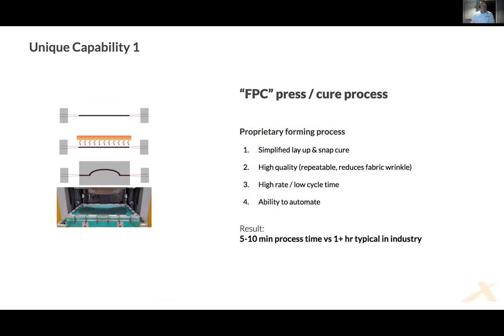The first area that we tackled is called the FPC process. This process is no longer using an autoclave and a slower ramping up, dwell and ramp down process, but is now a fast press curing under vacuum. This allows us to reduce the time taken to manufacture the component and subsequently the impressions per tool, so increasing volume. We typically see the whole process down to about 9 minutes at the moment, and there's still further that we can do. That's on an example of a component that took well into about 3 hours to make by hand.